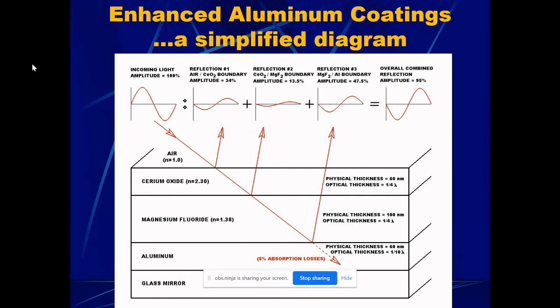And then finally the light hits the aluminum boundary, but by that point, we've already reflected close to 45% of the light by the dielectric. So the aluminum coating is going to reflect whatever else is hitting it, and it's going to take a 5% loss. So basically we have 3 reflections that are adding in phase, as you can see here, resulting in an overall reflectivity up to 95%, which is pretty good.